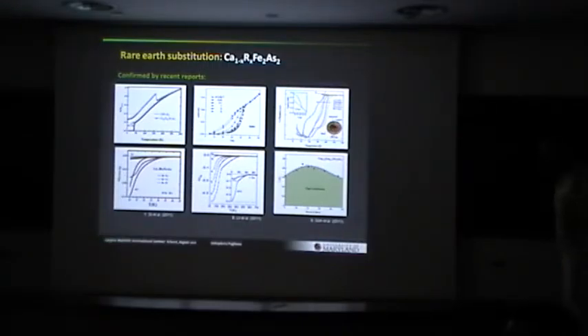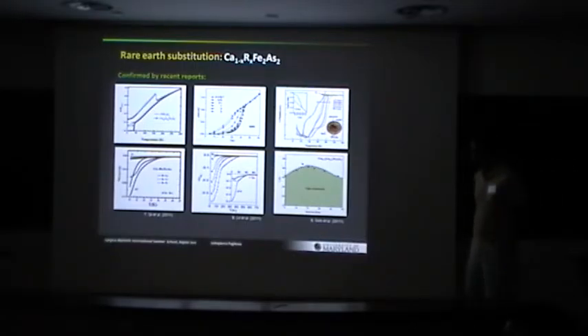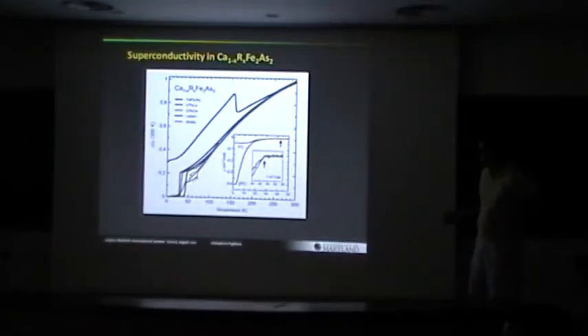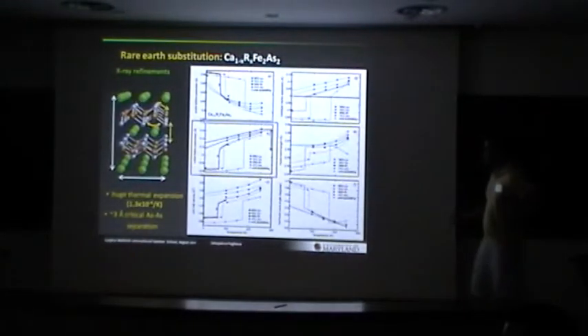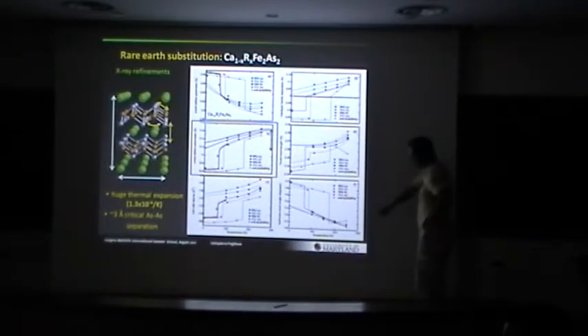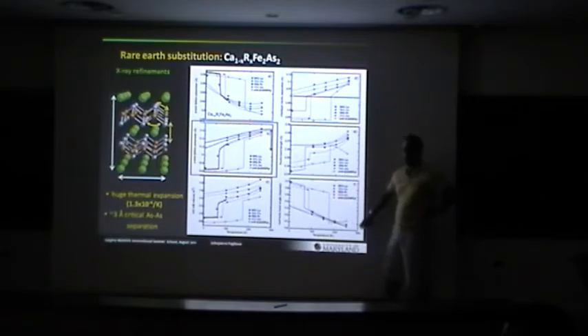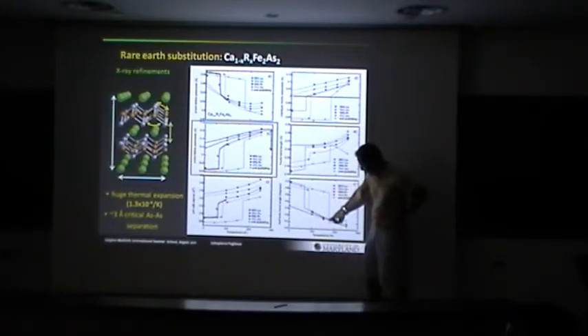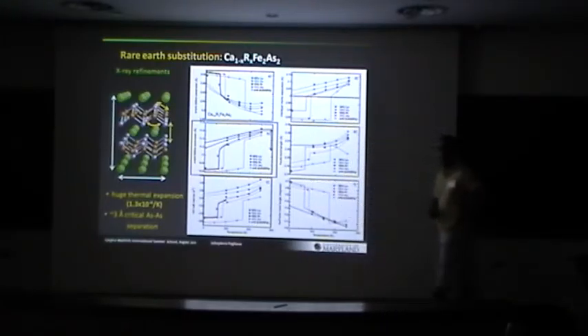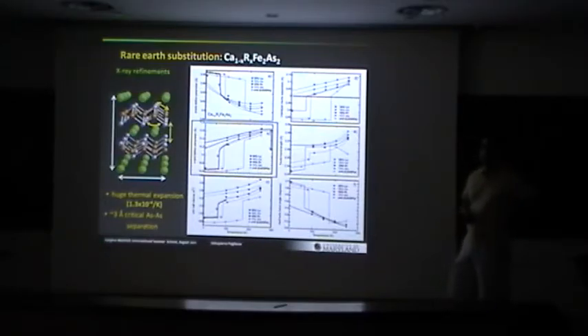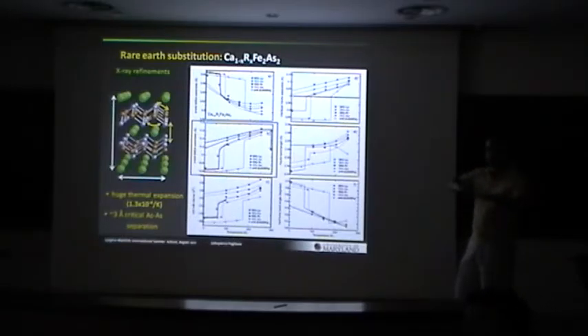Okay, so there's this correlation with the iron arsenic bond angle that we've seen earlier in the week. I don't know if this is a relevant question or not, but how does this structural transition, this collapse, fit into that picture? Yeah, so here's the bond angle as a function of temperature. So after the collapse, calcium starts close to ideal, 109.5 is ideal, and it goes away, and the ones that undergo the collapse go really far away. Okay, but they're not the ones with the highest TCs? They all show fairly high TC. You can understand that by just squashing this layer so that the angles distort.